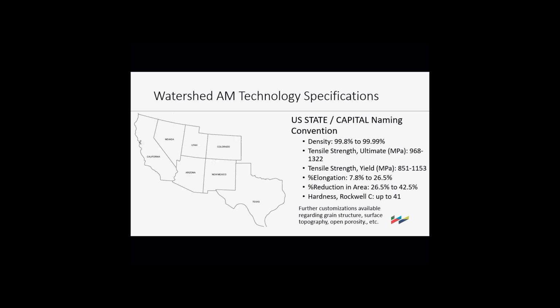And then we have densities up to 99.99%. You've got tensile strengths of almost 1,000. Yield strength over 800. And then one of the things with medical devices, you want it tough. So they look at elongation, that it doesn't crack because of the elongation. So you want it in your body to be tough and actually a little bit of flexibility, which you're able to build in with 3D printing, which you can't do with subtractive.